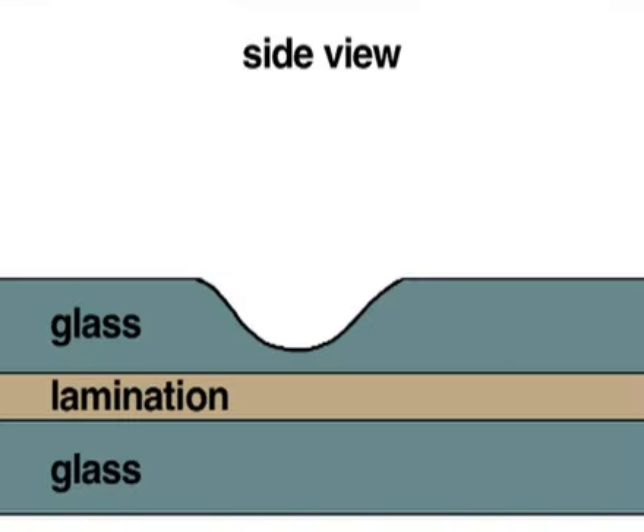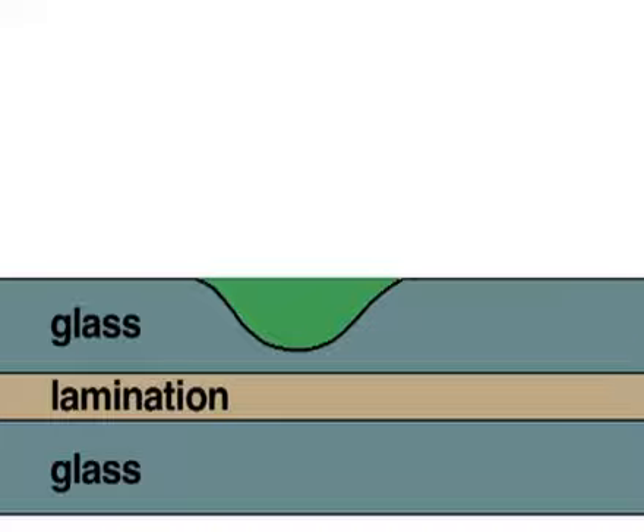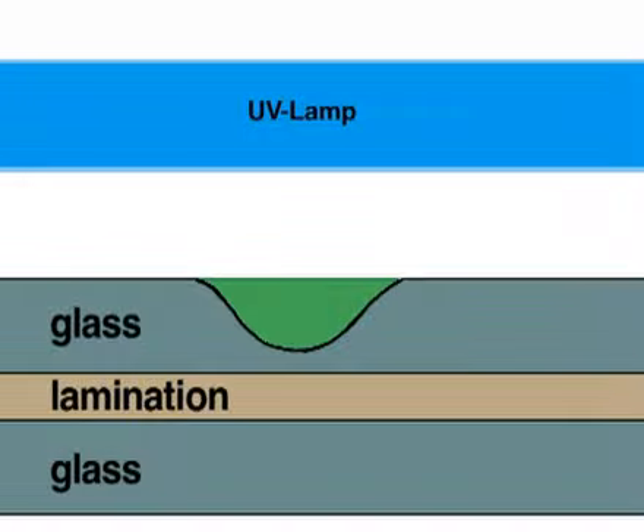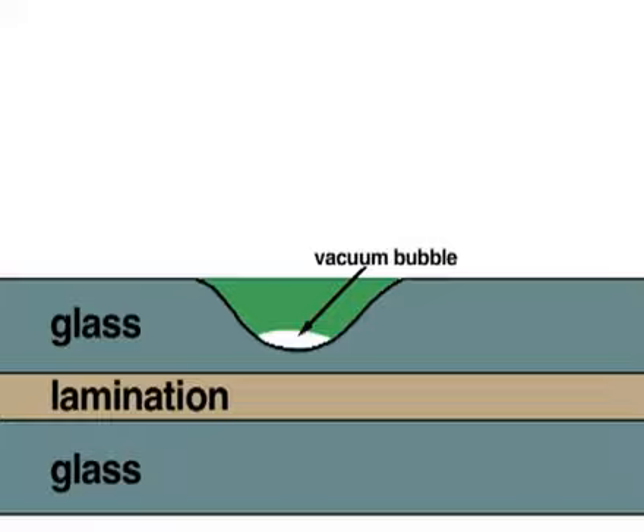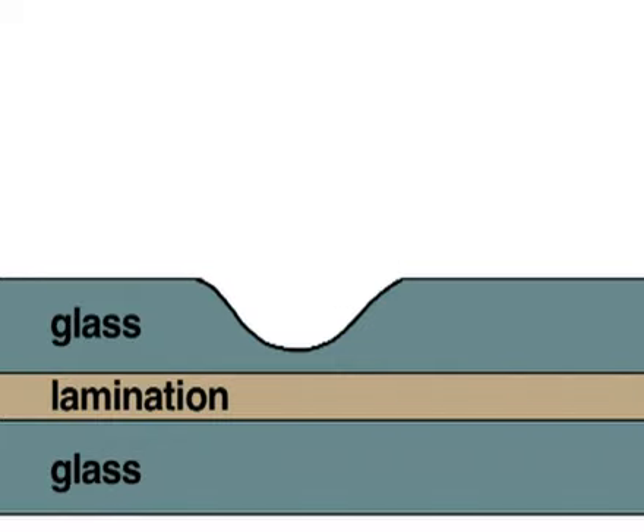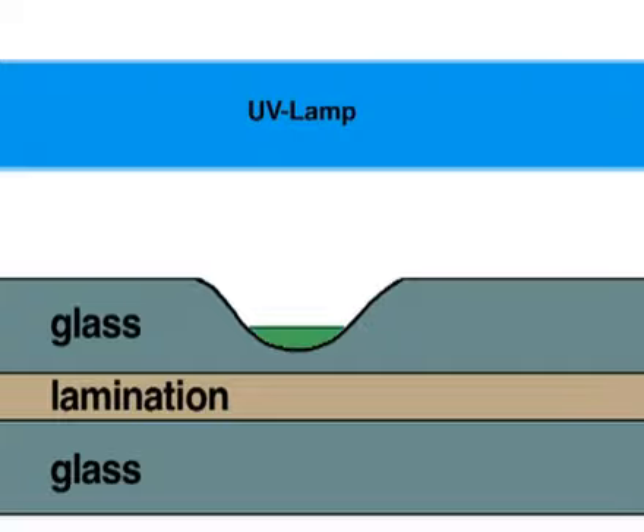Deep chips and drill holes have to be filled with finishing resin in a step-by-step process due to the polymerization shrinkage. If major chips of the outer glass layer, or drill holes, were filled and cured in a single process, this would lead to capping on the surface as the resin cures from top to bottom. As a consequence, on the bottom of the glass layer, i.e. on the lamination, one or several vacuum bubbles would form, since no more fill material could flow in from the surface. Therefore, fill drill holes and deep chips only step by step.